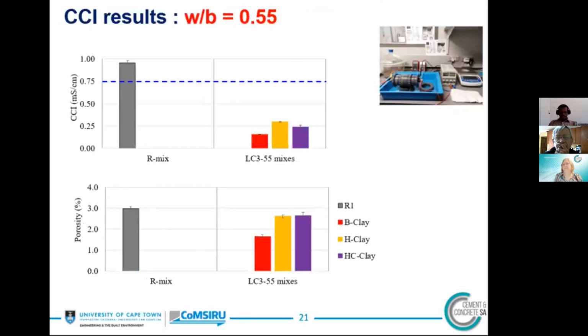Now here again is the case of 0.55 water binder ratio. All LC3 mixes have values less than 0.75 in the case of CCI. And the reference mix has a value between 0.75 and 1. So here in general, it means that the LC3 mixes are better than the reference mix in terms of resistance to chloride ingress.